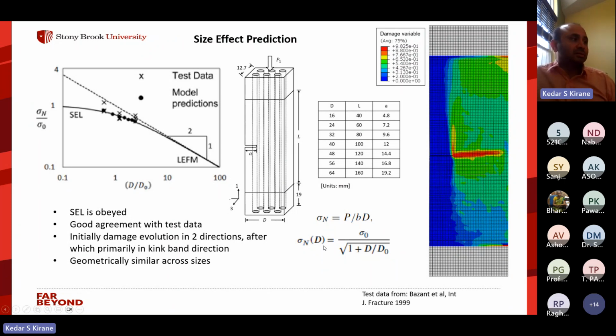And we can see that the model can predict and capture the size effect correctly. It obeys the size effect law, and it also matches the test data. Again, this kind of agreement has not been shown in literature by any other model, or they have not even probably checked for size effect. So it's pretty pleasing that it can match this well.